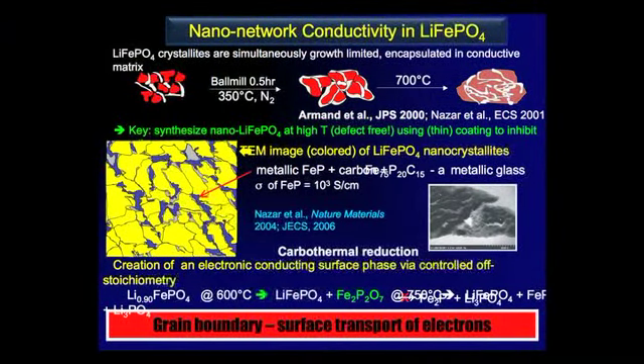2001 is when we actually published this. And Michel Armand at the time was a step ahead of us. They were looking at carbon nanopainting, as they called it. This is our work where we took carbon precursors, milled them up with the lithium iron phosphate precursors, milled them up with carbon, and effectively used these as a kind of shrink wrap to constrain the size of the particles. So we ended up with composite materials that were about 10 to 15% carbon, in which we constrained the growth of the lithium iron phosphate.